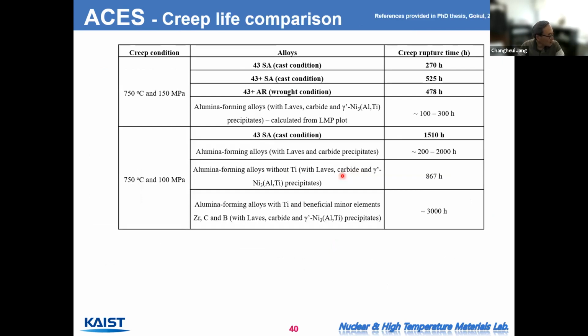And this is a summary of the creep test results of our alloys. So this one is at 750 degrees and 150 MPa. Our test alloys have around 500 hours of creep life. This one is significantly longer than the AFA alloys, but at a little bit lower loading. So we have 1500, and we have a comparable creep life to other AFA alloys.